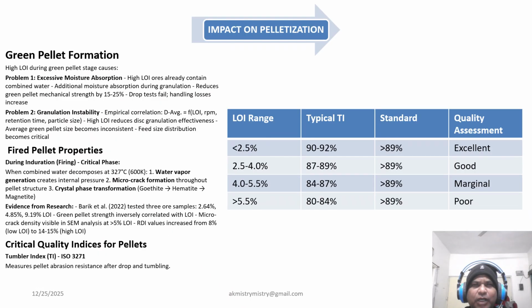Now coming to the high LOI effect, pellet formation and its consequences. There are two ways. The first, it absorbs excess moisture during granulation, weakening green pellet strength by 15 to 25%. This is one of the highest impacts.